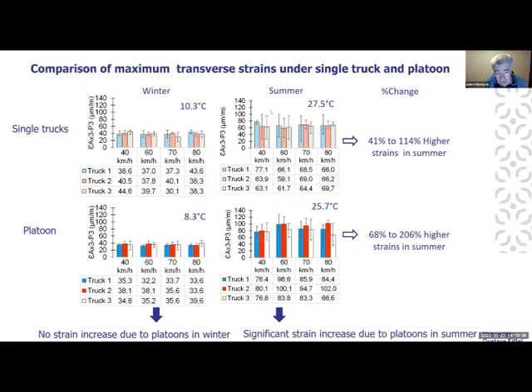In the summer, it's very different because the temperatures were higher, 25 to 27 degrees in the base layer. We had much higher strains under the second and third trucks of the platoon in the summer than under individual trucks. And if you compare the change of strain between winter and summer, the increase of strain is also much higher under the platoons than under the single vehicles due to the strain accumulation effects. So the idea then in the project was to try to model and reproduce these effects.